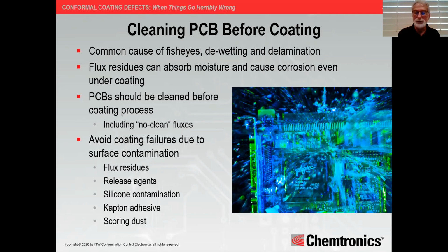There have been some instances where these are rooted back to the use of no clean fluxes. It is not every no clean flux. It is not every coating. It's just certain combinations. People coat over no clean every day. But that potential exists for that one in a million shot of having a coating and a no clean flux residue that are incompatible with each other. So we always recommend cleaning before you coat.